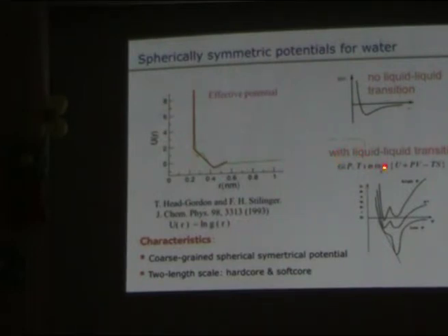the phase transitions, we can look at the Gibbs energy for the system. Basically, it's the internal energy plus PV minus TS, the entropy term. So if we just use the simplest case, for instance, temperature equals 0, you can see that this is really similar to other potentials because we have two length scales. You can have one here and the other one here. As you change the pressure, you can gradually switch the stability of these two states.